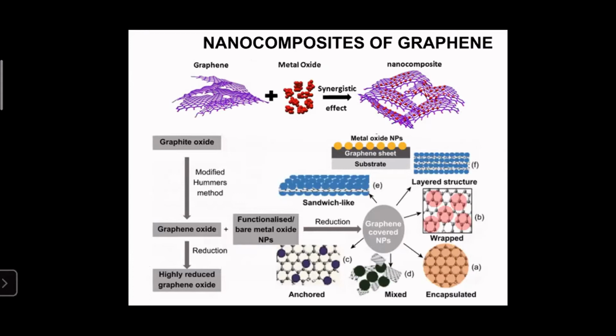And about nanocomposites of graphene. Graphene can form nanocomposites with various species, including metals, metal oxides, etc. These nanocomposites have synergistic properties unattainable by the individual components. Usually, graphene-based nanocomposites are prepared using graphene oxide assisted methods. This is because of the many functionalities available on graphene oxide, which can successfully incorporate different species by covalent binding as well as polar interaction, etc.